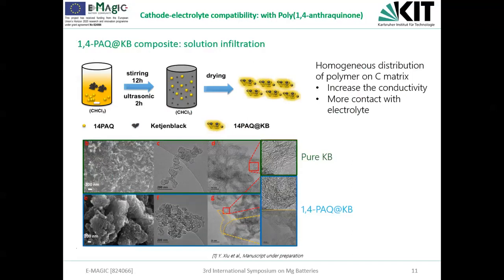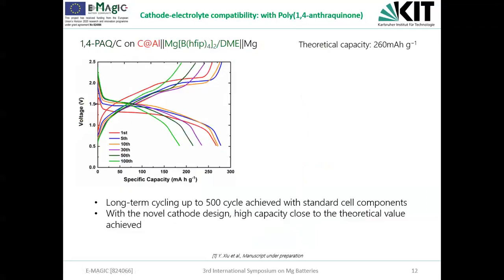So here I show you some typical electron microscopy images. Basically, the first column is the pure carbon matrix, while the second column is the carbon with the active material loading. We see the amorphous region, which was marked by these orange colors, is dispersed well on the carbon matrix. Then we tested the battery performance using this new cathode design, coupled with the borate electrolyte. Here we see that we could run a cell for up to 500 cycles with standard cell components, which indicates good compatibility.